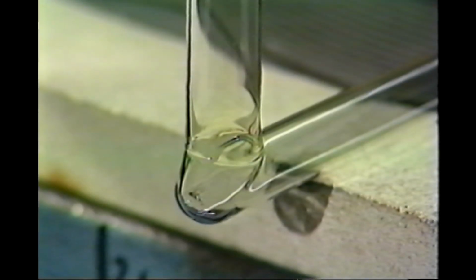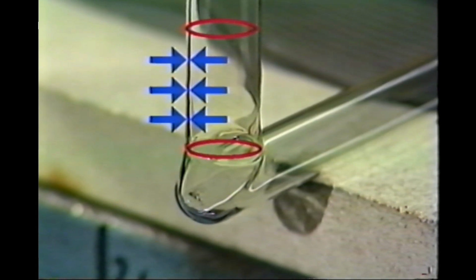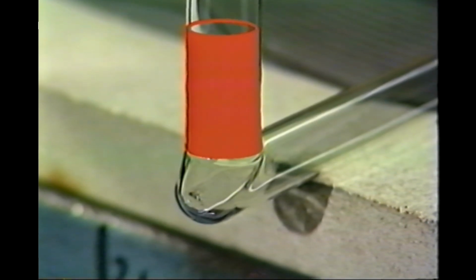Having produced a good right-angle electrode joint and thoroughly annealed the glass, the return bend can now be made. The wall thickness of the electrode at the end of the joining operation must be correct prior to melting and bending the return. Set up a fairly strong flame wide enough to melt a 2-diameter area of the electrode glass.